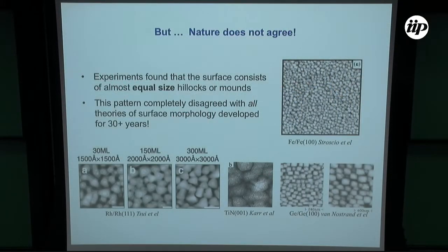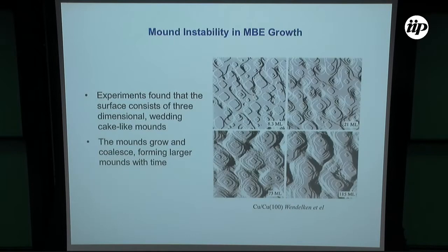But when the experiments were done, what was found is that, lo and behold, there is a characteristic size in every one of the experiments that people did. This is rhodium on rhodium, work with Sui at UNC Chapel Hill. This is tin. This is germanium on germanium, done at University of Michigan. And iron on iron work was done at NIST by Stroscio. And a very nice looking one, which tells you what happens, is the work of Wendelken at Oak Ridge. This is copper on copper.